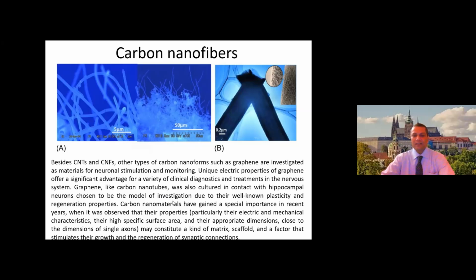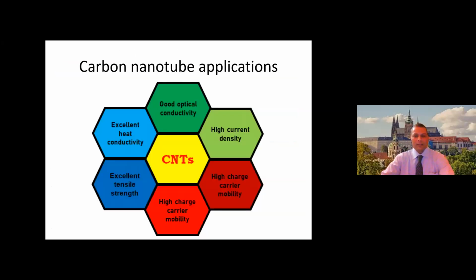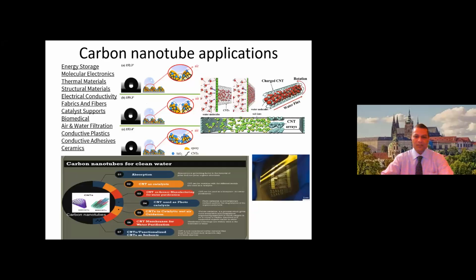Just pyrolysis is not enough for nanofiber formation, but it has to be ground and mechanically split to have nanostructures. Maybe all of them are not of the same length and same diameter, but they can be used as a substitute for carbon nanotubes. So the enhanced features of conductivity with respect to heat, electricity, and mechanical performance are definitely by means of using carbon-based nanostructures.